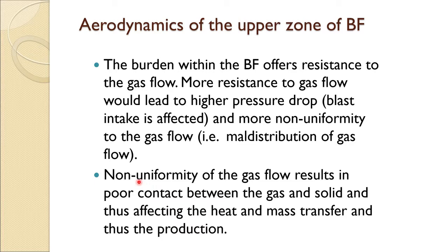Because gas will always try to take a least resistance path, it may bypass some of the pores or voids, where it is least resistive, near the wall and like that. So there would be very little gas and solid contact. The gas is the CO and nitrogen which is coming, which gives the sensible heat to the charge, and CO also takes part in the reduction. That is not going to take place effectively, so that is going to affect the heat and mass transfer. So, gas flow phenomena is most important in the blast furnace from the production viewpoint, and that is why this topic is called aerodynamics.